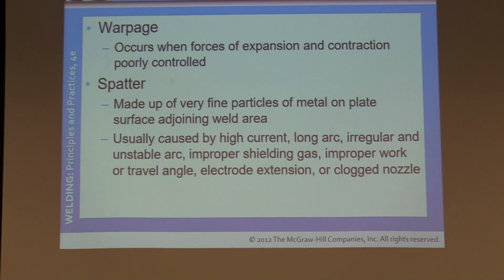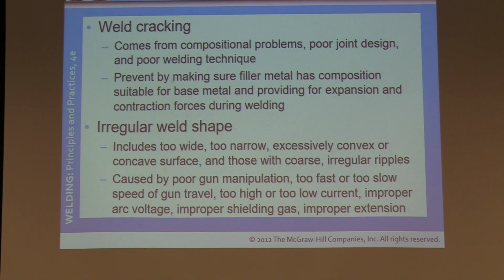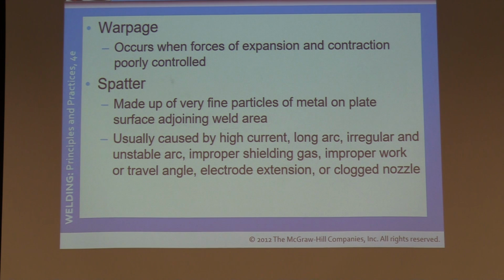Okay, other defects. Warpage. It occurs when forces of expansion and contraction are poorly controlled. Most of us know what warpage or distortion is. Okay. Spatter. Made up of very fine particles of metal, usually caused by high current, long arc, irregular and unstable arc, the improper gas, improper work or travel angle, or clogged nozzle. Usually 90% of the time it's either your current is too high or your wire speed's too high, and you're staying too far away from the material itself. Okay? A lot of welding machines get blamed for spatter when it's technically the welder that needs to change it up a little bit, and or even their technique to reduce the spatter as well.